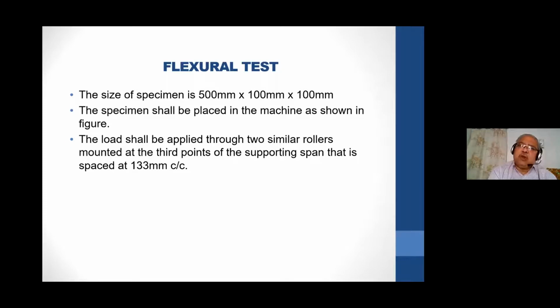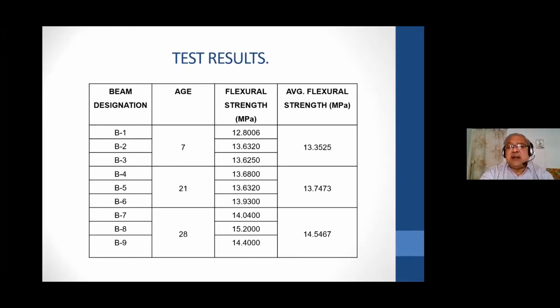Because tensile strength is good, the compressive strength is naturally very high. But at the same time, what is its behavior under bending, under flexure? That also had to be verified, and hence we prepared a specimen of 50 centimeter long, 10 centimeter wide, and 10 centimeter depth. This specimen was placed in the UTM. The load was applied through two similar rollers mounted at the 1/3 points of the supporting span, placed at almost 133 mm center to center, and the test gave really wonderful results as far as the average flexural strength is concerned.